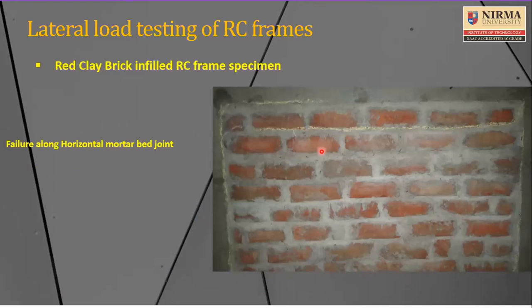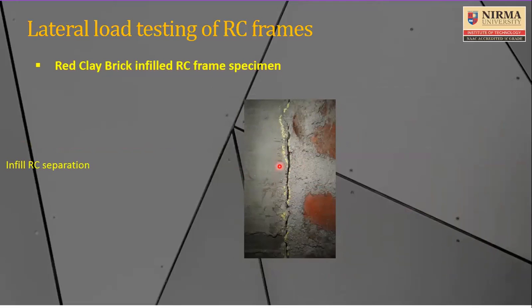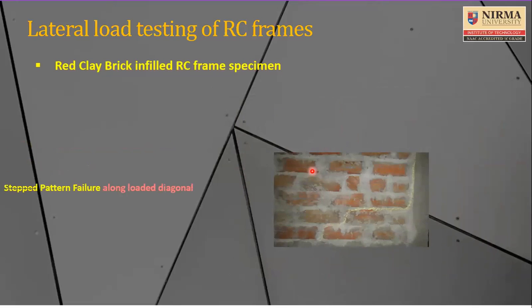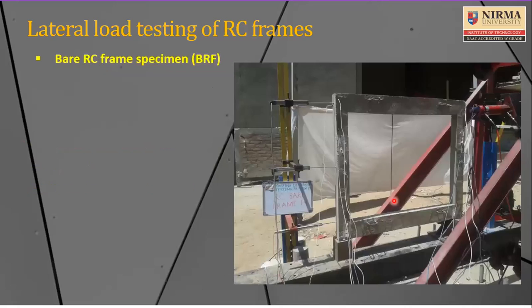clay brick has very good properties, very good compressive strength, and its modulus of elasticity is, of course, very less as compared to the RC frame, but it has a very good compressive strength compared to the reinforced concrete element, and therefore it is undergoing that horizontal bed joint failure and vertical separations of the frame along with the bed joint. And you can see some step type failure is also observed in the red clay frame.